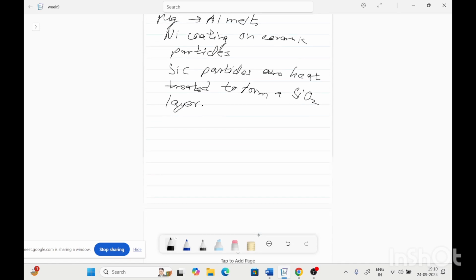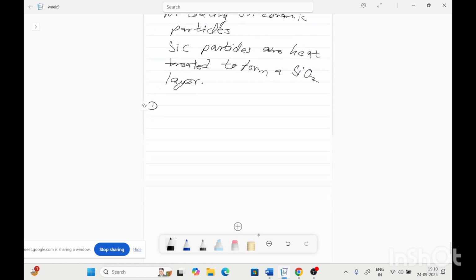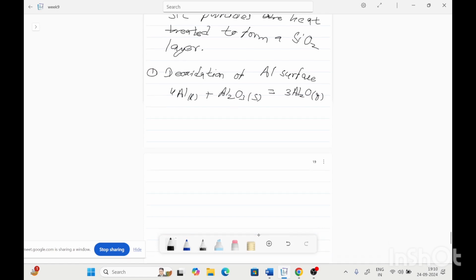So how is this wetting improved in the silicon carbide addition? So there are three steps. So first is the deoxidation of aluminium surface, to expose the fresh aluminium for the reaction. So the reaction can be written as 4Al, which is in liquid state, plus Al2O3 solid ceramic particle, that gives 3Al2O gas. So this will deoxidize the aluminium surface.